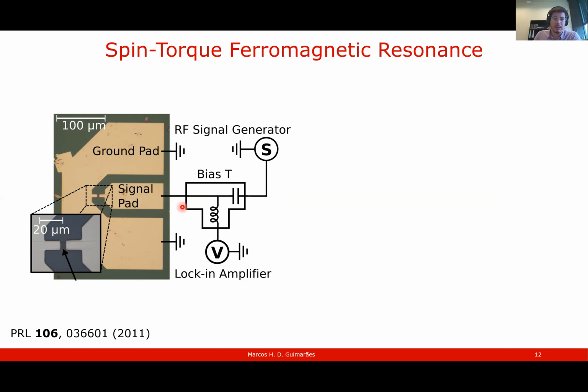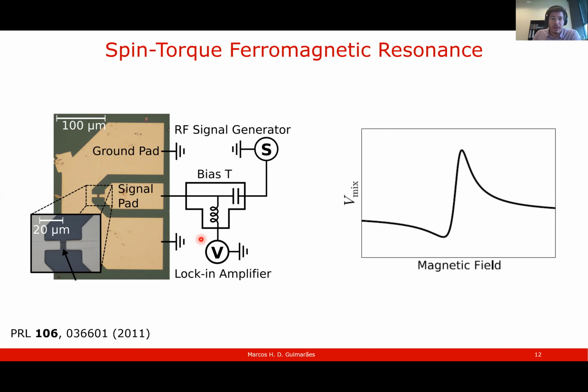When the frequency of this RF current matches the Larmor precession frequency given by an external magnetic field, then we have a resonance condition. And this we can read through a lock-in amplifier. We read the voltage as a function of applied magnetic field for a fixed applied RF current frequency. So when the Larmor precession frequency given by the magnetic field matches the frequency of the current, we have a resonance line in our voltage detection that looks more or less like this.